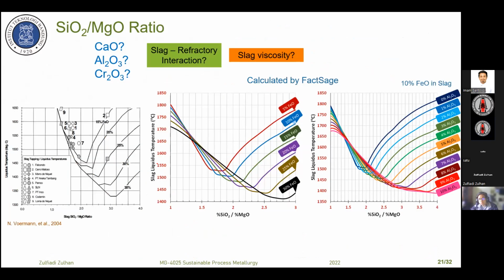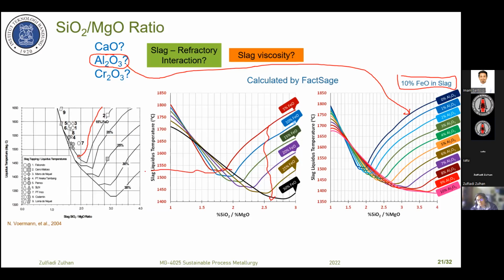And then last year, we made a calculation with FactSage. We observed that the proportion of alumina may influence the liquid temperature. For example, here, according to the calculation by FactSage for 10% iron oxide slag, maybe in that line here for 10%. I don't know why it's a little bit different between the calculation and this diagram; they're not 100% similar. If we add alumina 1%, we can reduce the melting point, especially when the silica to magnesia ratio is around 2 in this area.